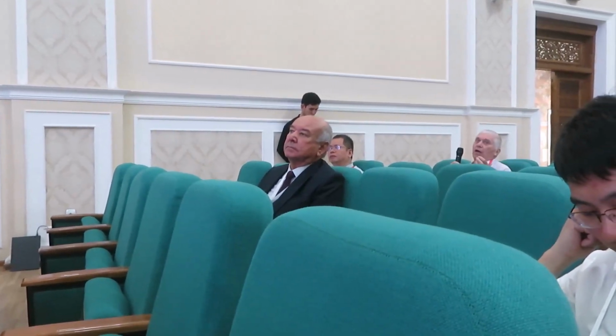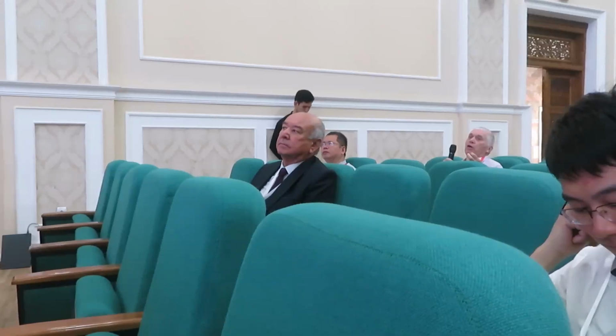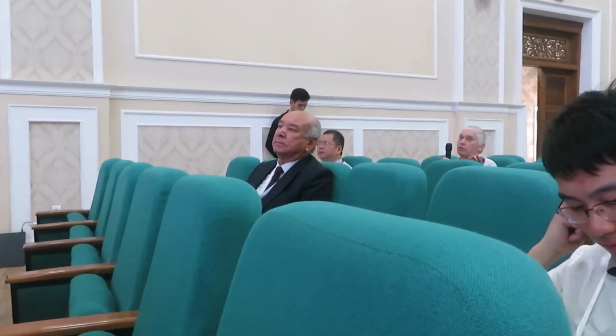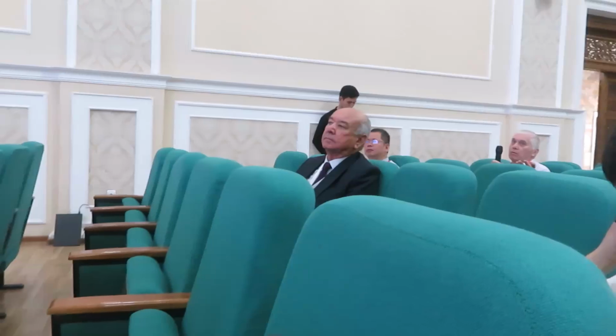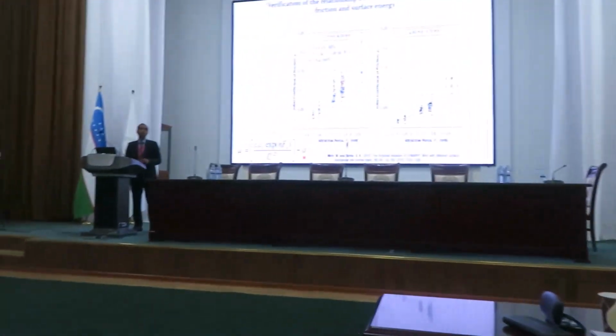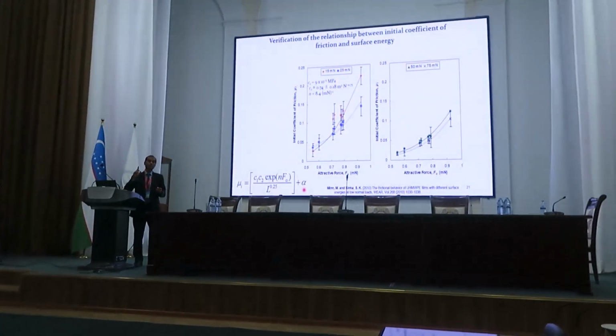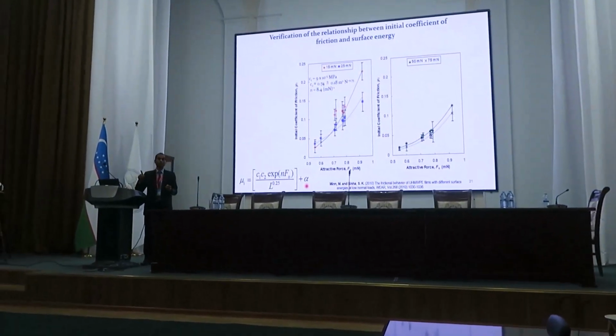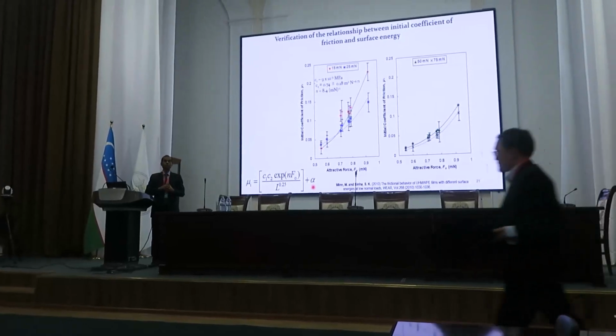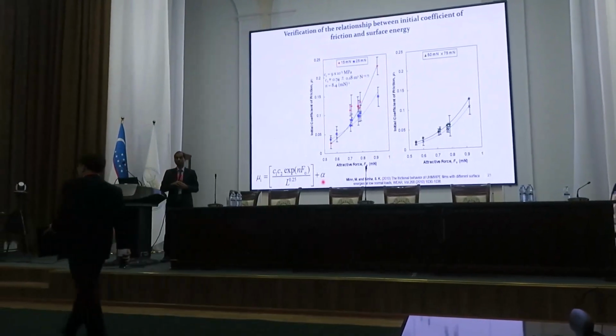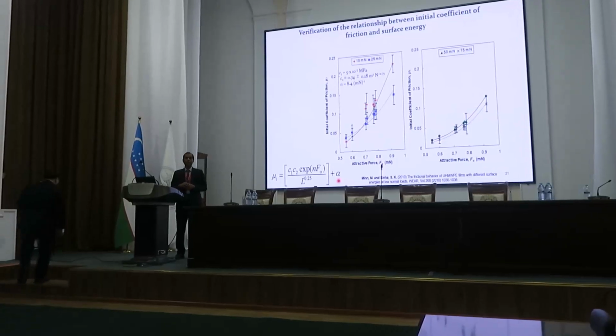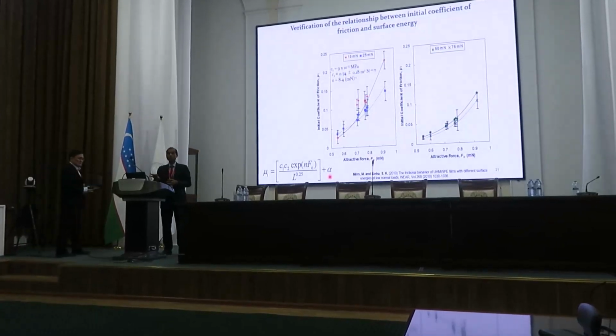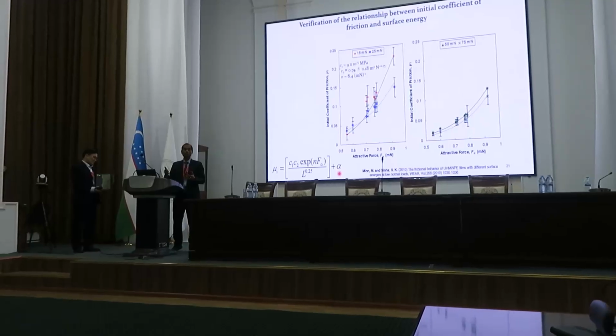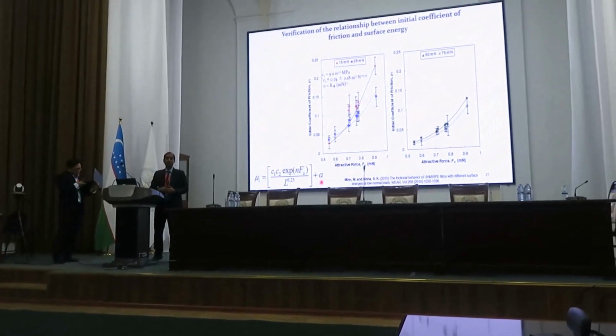So how did you calculate it? So we calculated a pull-off force by measuring the water contact angle and surface energy. So we measured the surface energy of the interface, and that is how we got the pull-off force. And the influence on friction? This shows the initial friction, that means before the wear took place, the very, very beginning of the friction only.